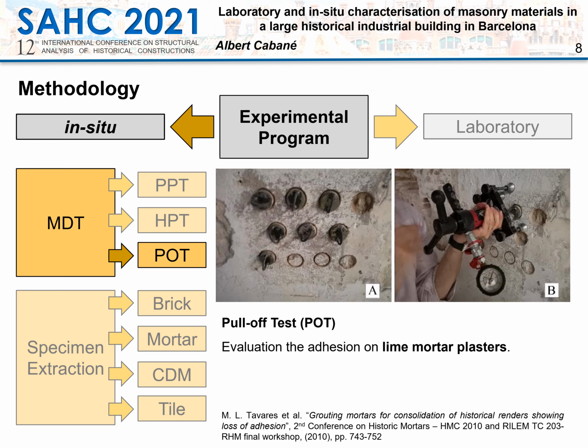The third in situ technique considered was the pull-off test, executed on the same 4 zones of mortar plaster where the first test had been carried out. The pull-off test allows to measure, using a dynamometer, the perpendicular pull-off load applied on a 50 mm diameter metal disc. These pull-off forces evaluate the adhesion strength of the lime mortar plaster on the masonry.